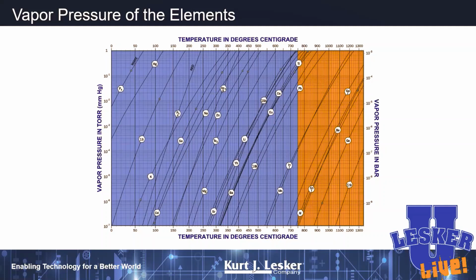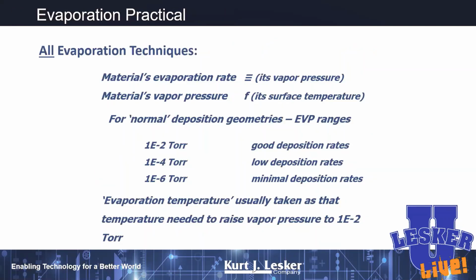That means the zinc will likely not attack our boats. We won't get some sort of violent reaction between the zinc metal, for example, and our tungsten boat. As I mentioned, typically for thermal and e-beam evaporation, you want a vapor pressure somewhere in the 10 to the minus 2 to 10 to the minus 4 range. Much below 10 to the minus 4, you're not going to be able to read much of a deposition rate on your quartz crystal microbalance. So think about being in this range here.